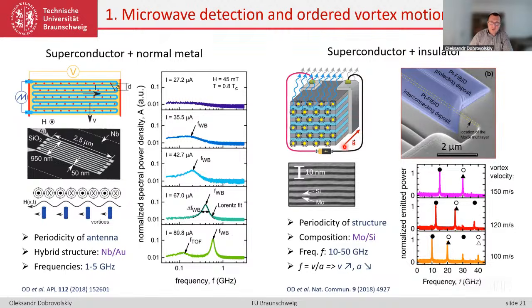Magnetic field is applied as shown here, into the screen, resulting in vortex motion from bottom to top. And this geometry is shown in this cartoon. So basically, this is just a scanning electron microscope image showing where the many layers are located, but they are not seen at the scale of the image because of very low contrast and the scale bar here. So just about 5 nanometers for the pair of molybdenum and silicon layers.